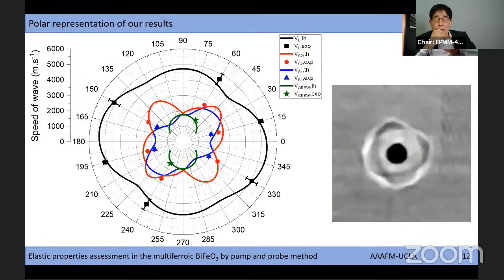Finally, we have wavefront curves within the surface plane that can be compared to the time-resolved images. Here the longitudinal acoustic phonon in black is too fast and is no longer present in the image, while the other slower waves are recorded. In the polar representation, we can clearly see a flower shape reproducing the experimental pattern with 4 petals in the vicinity of the same direction. So there is a nice agreement between the experimental results and our calculation.